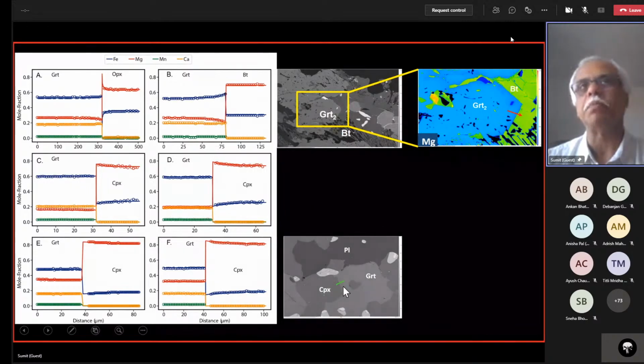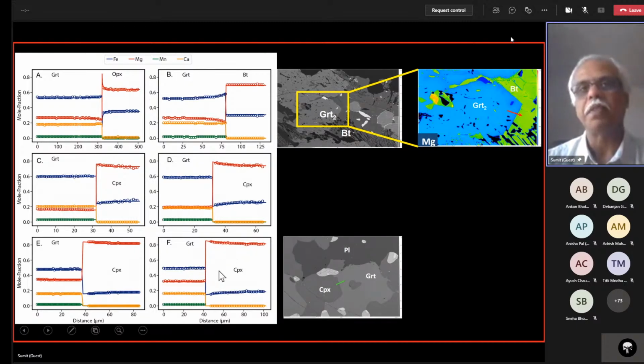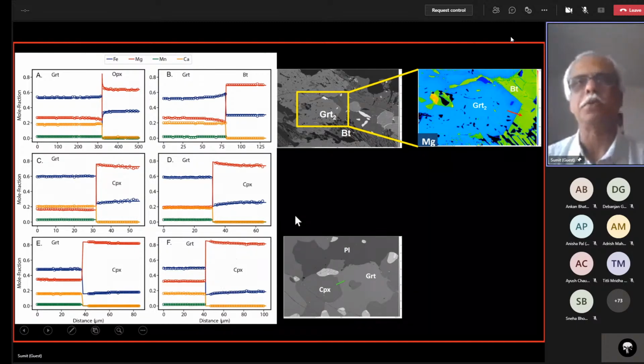So the same sort of thing you can get between garnet and clinopyroxene. This is a picture of an area. So you see that the zoning is actually very close to the rim, so you have to be careful to measure really close to the rim. But if you do that, you see here, for example, now the clinopyroxene is the one that's zoned, the garnet is not, and so forth.